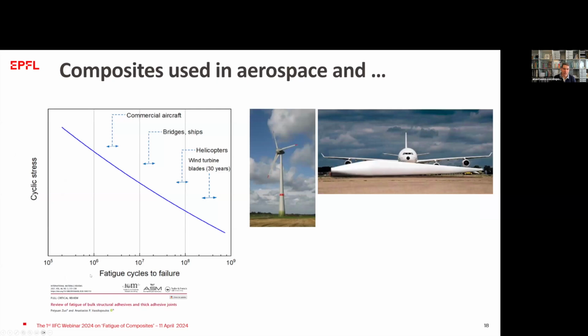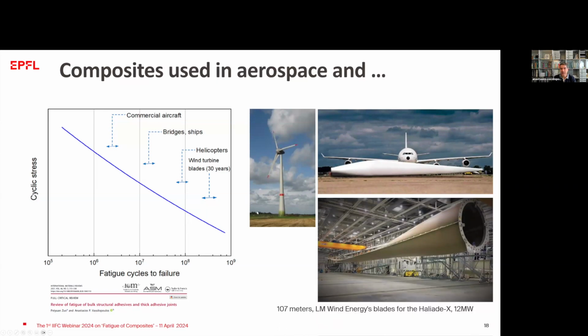We now have a lot of structures, like wind turbine blades, that are supposed to live for 25 years more or less, and they face more than 100 million cycles during their lifetime. We have helicopter blades approaching 100 million cycles. We have bridges and ships that, depending on the design and dimensions, might see more than 10 million cycles. So we have a lot of composite structures facing a lot of fatigue loads during their lifetime, and these structures are massive. You know about the longest blade. Today I think it's 120 meters. A couple of years ago the longest was 107 meters, made by LM for the offshore 12 megawatt machine they were preparing at that time.